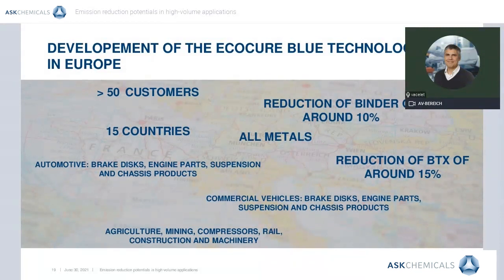All types of castings are produced with EcoCure Blue, from brake discs, engine parts, suspension and chassis products for cars or commercial vehicles, to castings for the mining, agriculture, rail, construction, or machinery industry. In all of these cases, the profits were able to compensate for the slightly higher price. It has been possible to reduce the percentage of binder by an average of 10% and at the same time reduce BTX emission by about 15 to 20%.